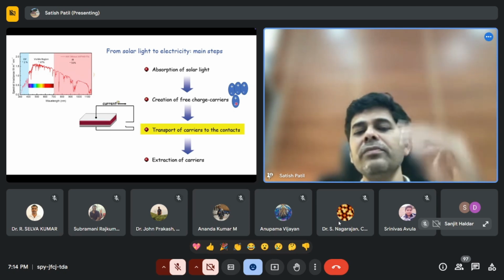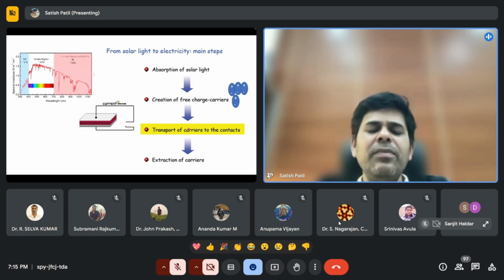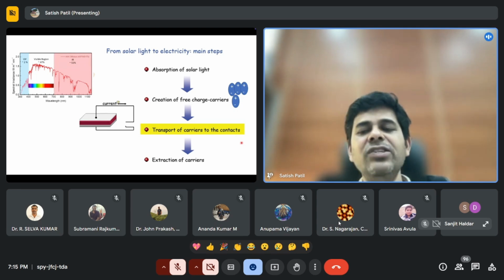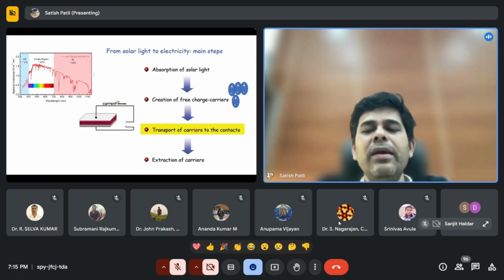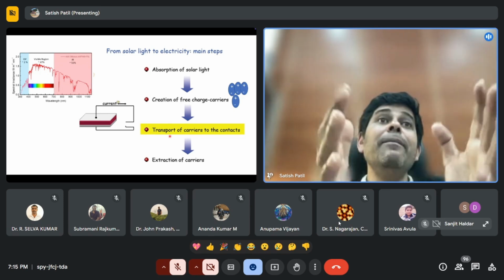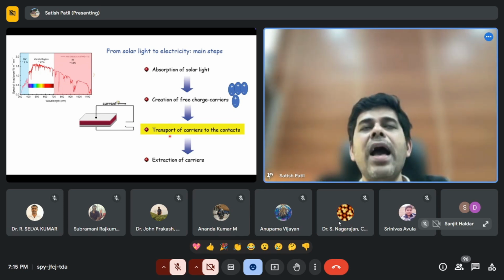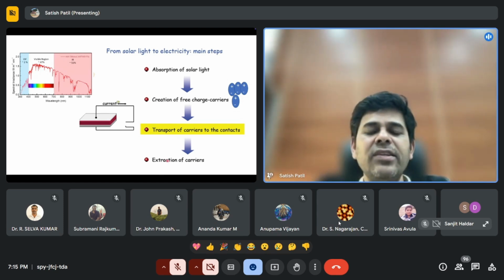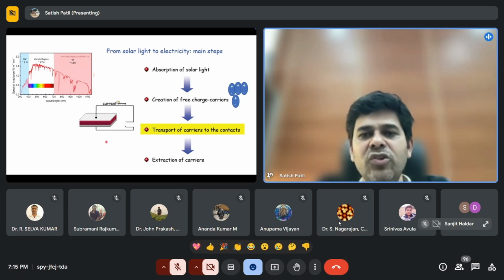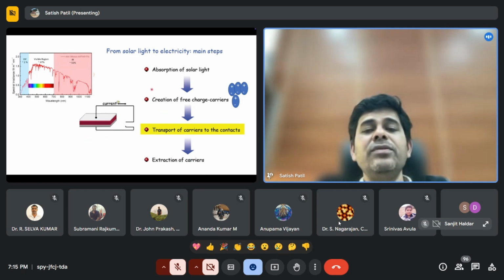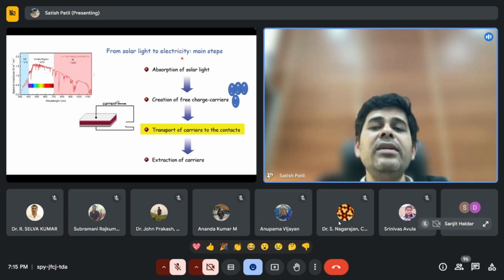These are bound pairs. As I mentioned a few slides ago, the transport of charge carriers to the contact is very, very challenging because these are very low mobility semiconductors. So eventually the efficiency is very low compared to conventional semiconductors because the mobilities are very low. Before you collect efficiently at the electrode, they recombine. So the recombination rate is very high in organic semiconductors. As a result, there is a major loss mechanism. Then you extract the charge carriers to the electrode, and eventually you convert into electricity. So these are the key steps of converting solar light to electricity.